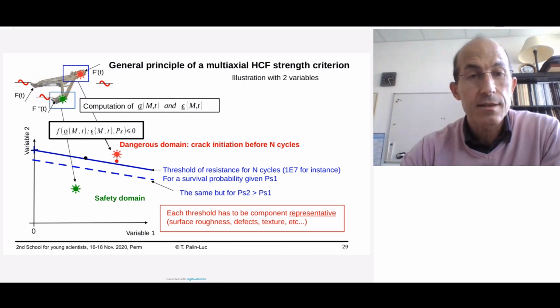If the point representing a material point of the component in this diagram is above the threshold, it is a dangerous case: crack initiation will appear before the given number of cycles with a given failure probability. On the opposite, if the representative point is below the threshold, it is in the safety domain, or safe side. According to the model, there is no risk of crack initiation before the given number of cycles and for the probability you are considering. Each threshold here has to be representative of the material state and of the component state, I mean, representative of the defects, the roughness, the texture, etc.